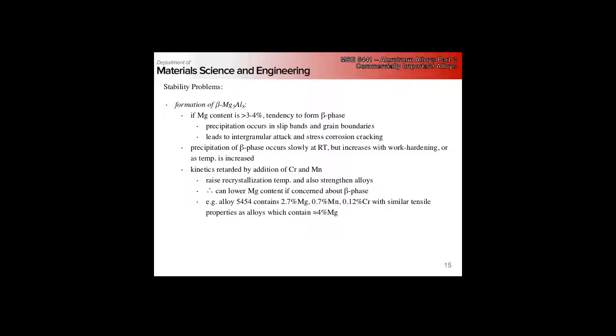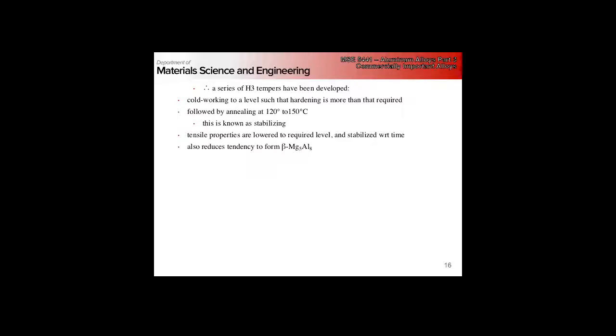Our Navy is not building new battleships or new destroyers every couple years, they stay in service a long, long time. They tend to age soften at room temperature, so we typically work these in what's called an H3 temper, which is where you cold work to a higher strength than you want, and then you do a short anneal at a slightly elevated temperature to exhaust softening, and this is known as stabilization.